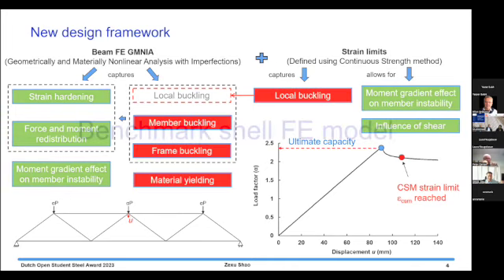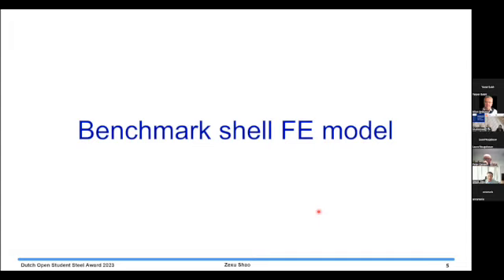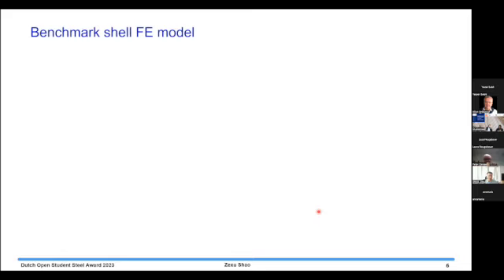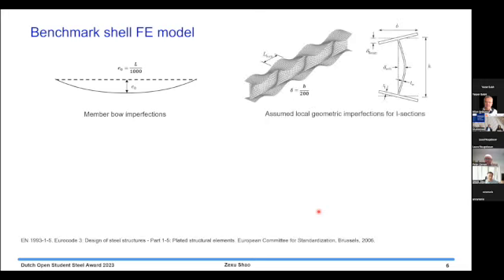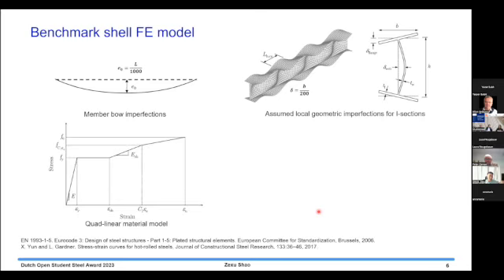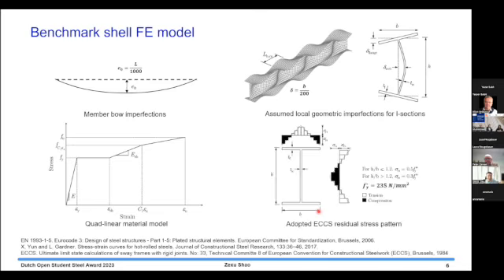So this is an overview of the proposed design method. But the primary purpose of my study is to investigate the applicability and accuracy of the proposed design method using the CSM strain limit. So we need to create a benchmark shell finite element model, which serves as a reference for comparison purposes. As we want to make sure this is a representative benchmark, everything required is modeled directly. For the member bow imperfection, I use the reference value of L/1000 for both in-plane and out-of-plane, and the local plate imperfection suggested by Eurocode 3 Part 5. The quad-linear material model is adopted here to capture the material nonlinearity, and the ECCS residual stress pattern is incorporated into our model as well.